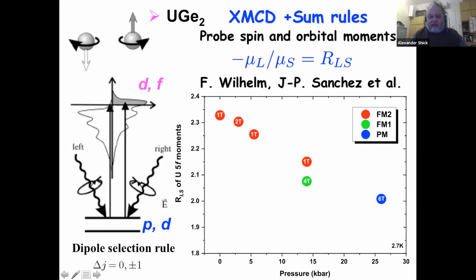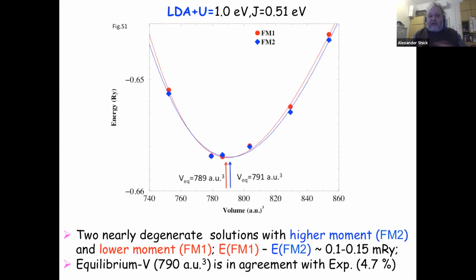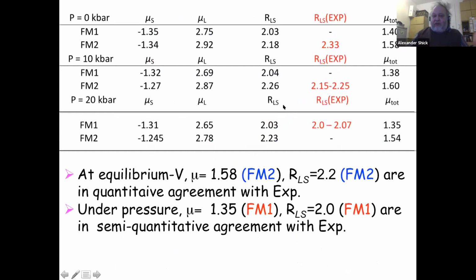So then, indeed, you wanted to check whether it comes out in the calculations. And the first thing we did was the calculation of uranium germanium-2 using LDA plus U. Eventually, we obtained two solutions: FM1 with the lower moment and FM2 with the higher moment. And if you look at the energy dependence on the volume, you see that near the equilibrium they are practically degenerate. So you don't need much energy to move from one state to another. And when we look at the properties of these solutions, like spin moment, orbital moment, and the ratio, we see that at zero pressure our ratio is close to the experimental value.